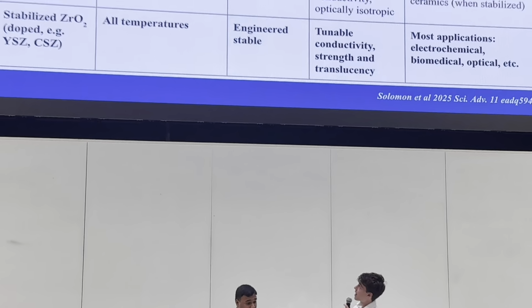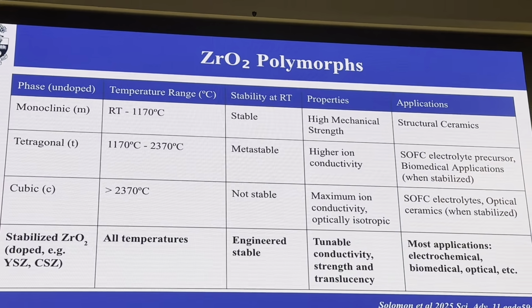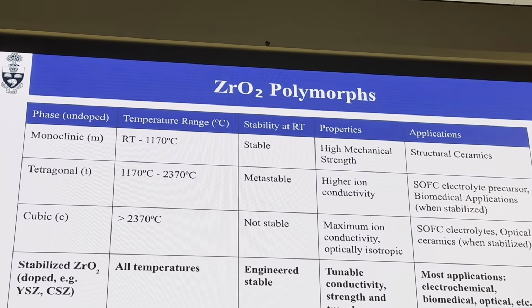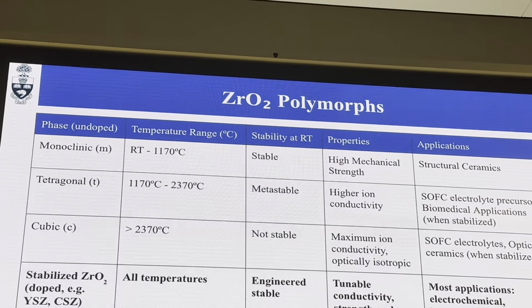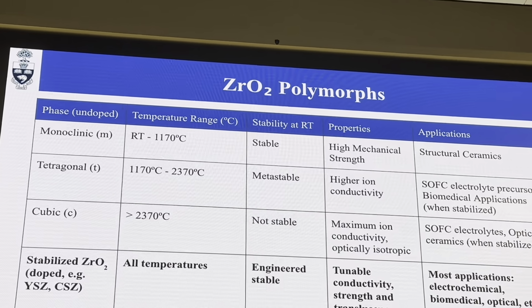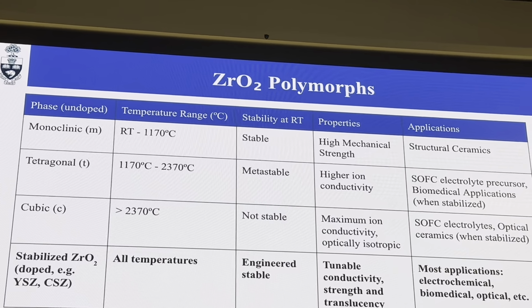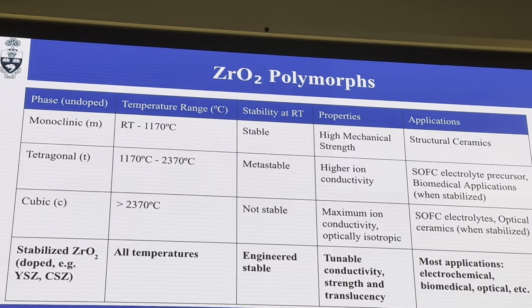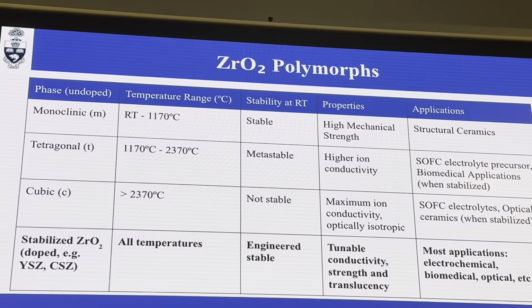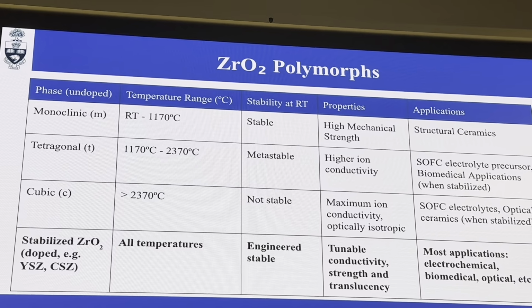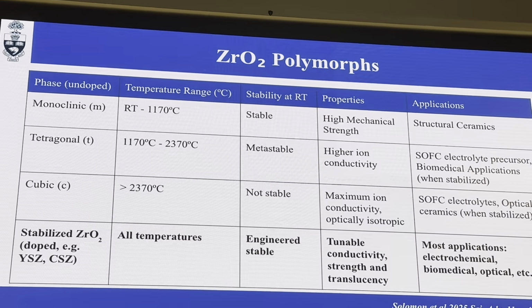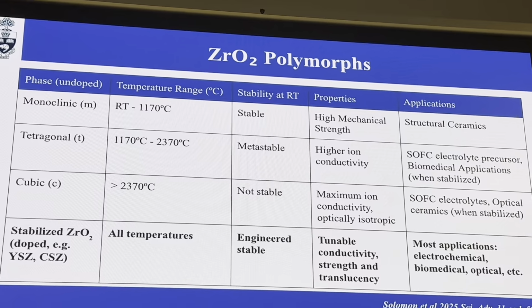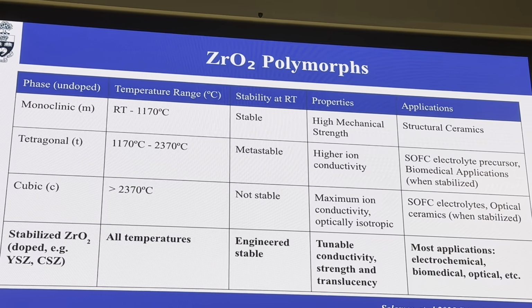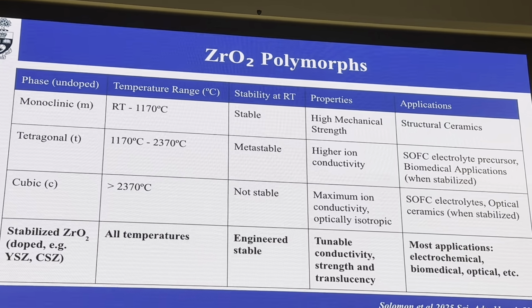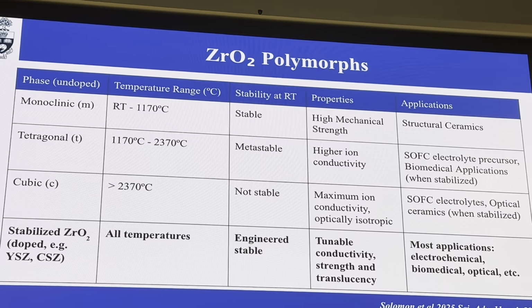Pure zirconia is not stable across all temperatures. At room temperature, zirconia exists in the monoclinic phase. As it gets heated up, we get the tetragonal phase of zirconia, and at the highest temperatures, we obtain the cubic phase. Now, the tetragonal and cubic phases are the most useful as they maximize ionic mobility and optical clarity. However, they are not stable at room temperature, as cooling these high-heat phases causes cracking due to large volume changes. To prevent this, zirconia is stabilized with oxides, such as yttrium, calcium, or cerium. This locks in the cubic and tetragonal phases at room temperature without cracking.